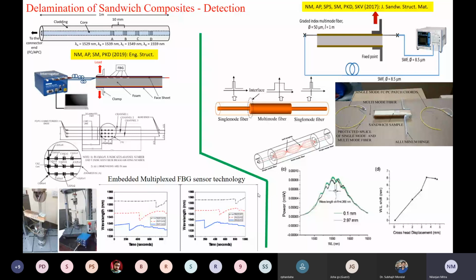We developed two different types of methodologies, and this was a project funded by the space agency ISRO. This was primarily meant for sandwich composites for rockets and other things. So how would you find out in situ, while the rocket is going up, for example, whether there is some region which is weak, or there is some kind of delamination? For that, we put in these optical fibers, and then we can do real-time monitoring of what is really happening at the interface between your glass fiber and your PVC, for example.